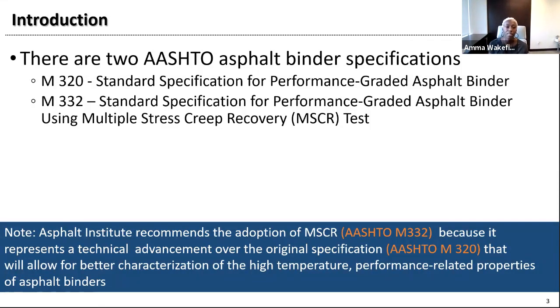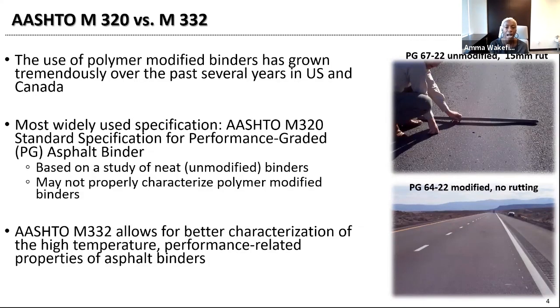The Asphalt Institute recommends that agencies adopt the MSCR specification, that's the AASHTO M332, because it represents a technical advancement over the original specification. As you learn, you improve, and you make changes, and you adapt. So this is a technical advancement over the original PG grading. The reason is it helps to better characterize the high temperature performance related properties of the asphalt binder. And how that even came about is because of how much polymer modified asphalt binders are being used. That usage has grown tremendously over the past several years, because of the need to meet the demand for higher truck traffic loading on our asphalt pavements.